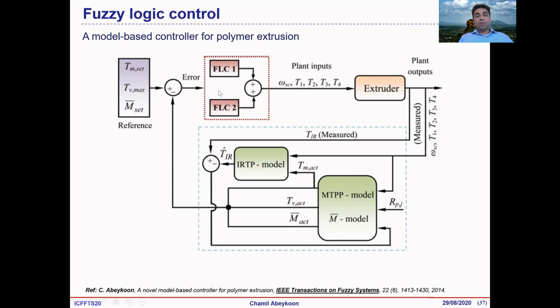Here we combine two fuzzy logic controllers, and we define the rule base for each of them. We define three reference settings. One is the melt temperature setting, and another is the maximum allowable temperature variation. If you remember, I mentioned before that melt temperature fluctuations can go up to 50 degrees or even 70 degrees on some occasions across a 38 millimeter circular cross section. It can be that big. Therefore, we define the maximum allowable temperature variation across the melt flow, the average melt temperature required, and also the required output of the process. These are the key parameters, the reference points.